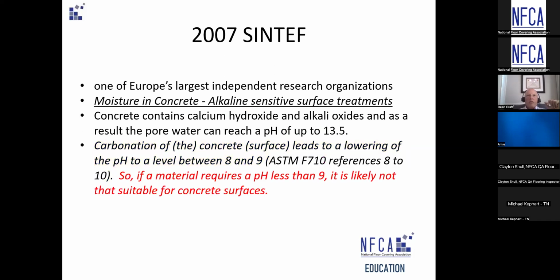One of the things to be aware of: if the material you're installing has a max pH limit of 8 or 9, it should give you pause, because all the literature expects average concrete to be 8 to 10. So if a product is listed with a max pH of 8, you really should be questioning whether it even should be used in contact with any cementitious material. And that goes for concrete, prep material, underlayment, things like that. So that's just one of the things.